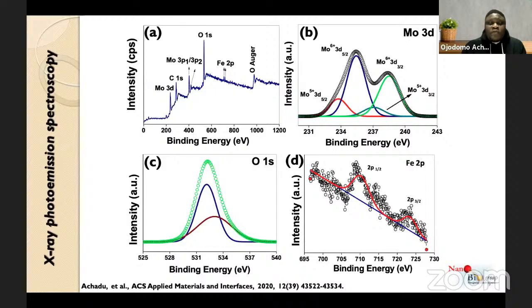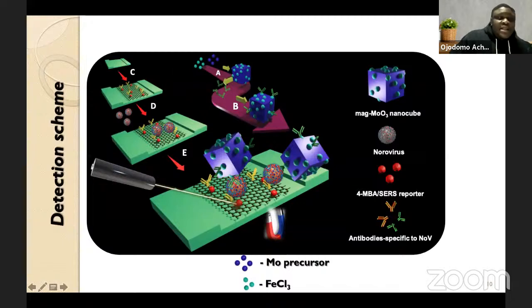Then we further did some structural characterization using XPS, whereby we were able to observe all the expected peaks based on the elemental and atomic composition of the material. Then further, the design and application of the nanocubes is now being explained here. This process, I'll take you through quite briefly. We prepared the nanocubes via a hydrothermal process, whereby we use a molybdenum precursor in the presence of ferric chloride, which is of course the magnetic precursor.